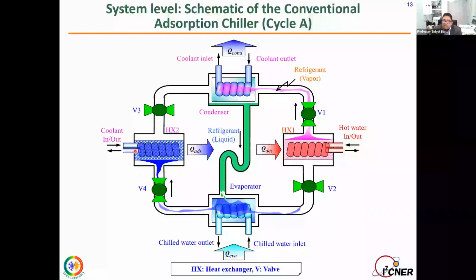So what happens here is after some minutes, like 7 minutes, most of the water vapor and the silica gel bed are in saturated condition. If I have 10 kilograms of silica gel in this heat exchanger, after 7 minutes about 3 kilograms of moisture can be adsorbed. So it is nearly saturated, and it is very difficult to adsorb more. In this sense, we have to change the operation mode of this cycle.